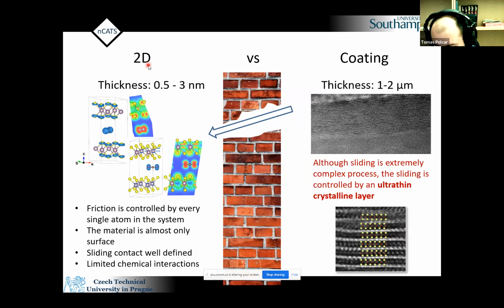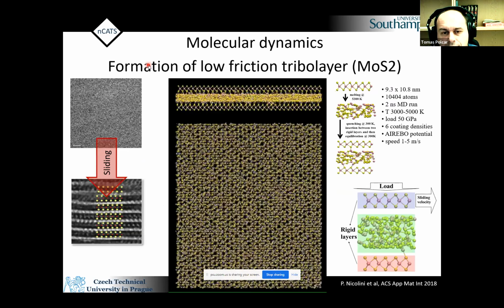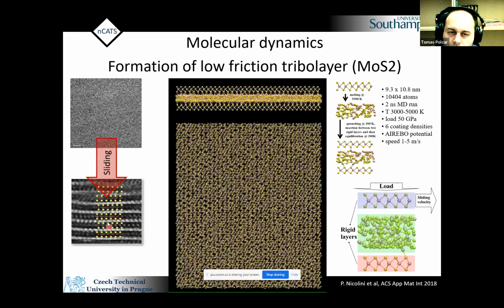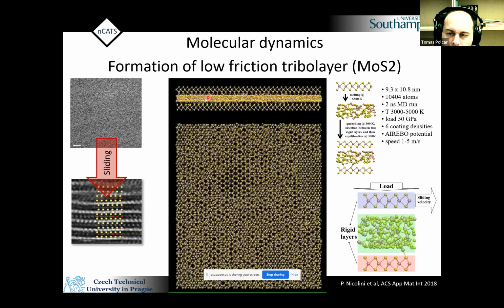So my first question was, how can we really form this tribo layer, which from amorphous somehow we get very nice crystalline. So we started with pure molybdenum disulfide. That's a relatively simple model, although it's not very simple to do in reality. And we slide, you see that we have two crystalline layers and some amorphous in between, and we slide them. In simulation, we did several coating densities and several testing parameters like different temperatures.